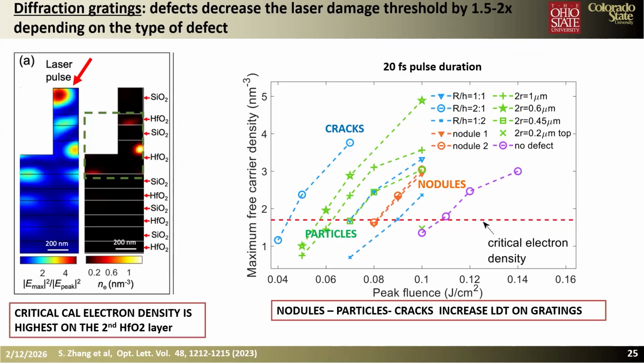Also with Ohio State, we have done studies on gratings. Gratings are very critical components in high peak power lasers. The studies show how, for example, cracks and particle nodules affect the laser damage behavior of the gratings. What you see here are simulations that show the electric field distribution within the grating. And you see that in the pillar where we have these steps, we have very high electric fields. And of course, that is going to be a source of, a precursor to damage.